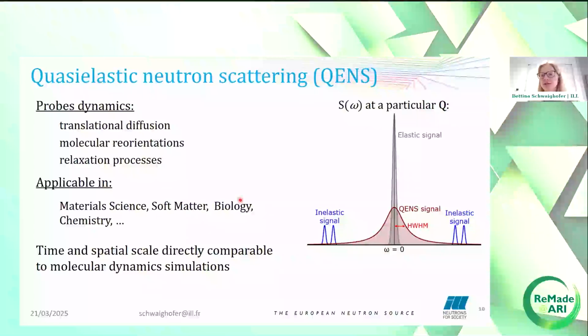Due to the large incoherent cross-section of hydrogen, QENS is particularly useful for studying proton dynamics, but it has also been very successfully applied to other ionic conductors or other elements like oxygen, lithium, and sodium diffusion, which is particularly interesting for battery materials.